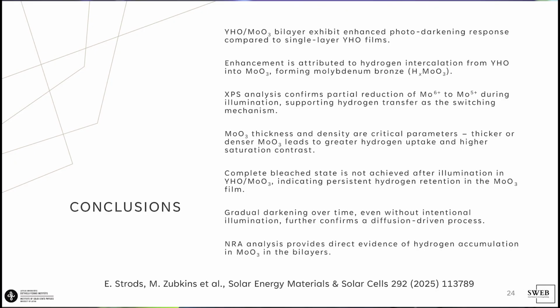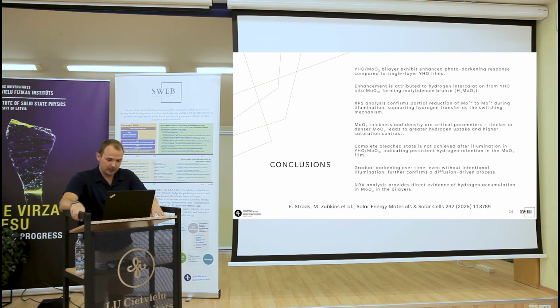This is one difference compared to yttrium oxide hydride with tungsten trioxide, because it is reported that if we heat that bilayer structure, it can be recovered. We tried yttrium oxide hydride with molybdenum trioxide and we didn't succeed. We also showed gradual darkening over time without intentional illumination, and nuclear reaction analysis showed direct proof of hydrogen diffusion into the molybdenum trioxide when it is in a bilayer structure.